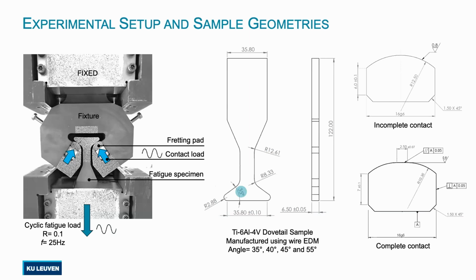One of the critical parameters here is this angle. If you search the literature, it can vary between 35 and 55 degrees, depending on the type of engine and the final application. But that can play a crucial role in fretting fatigue, because it can cause fatiguing of the sample at the wrong spot. You can have a competition between fatigue and fretting fatigue. That's the reason we selected the lowest angle, which could cause more stress concentration in our part, just to check the capability of AM materials.